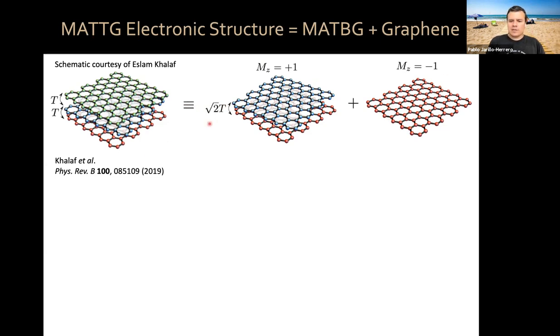So this is very interesting. If you remember from the first days, from Monday's lecture, and I also repeated it yesterday, the magic angle condition has to do with this interlayer tunneling. So it turns out for magic angle trilayer graphene, the magic angle is the one for the bilayer case times square root of 2, because of this square root of 2. So it's 1.1 times square root of 2, so it's about 1.56 degrees.